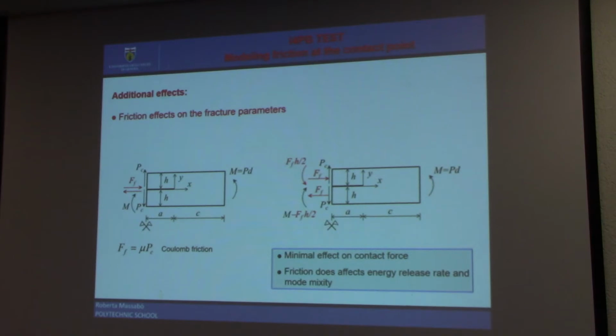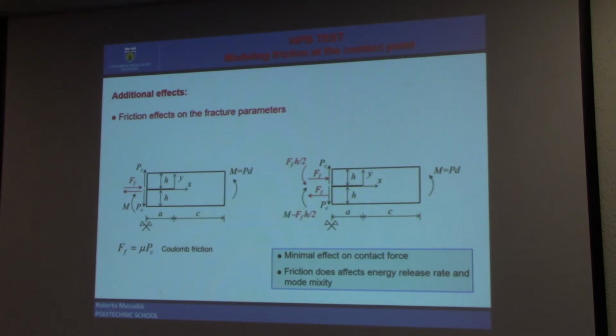So regarding friction, we account for friction using a structural mechanics approximation. Essentially, we consider Coulomb friction, and these two frictional forces are then transferred to the neutral axis of the beam, plus the compensating moment. And what we found out is that the effect of friction is minimal on the contact force, while friction does have a very important effect on the fracture parameters, as we already noticed in Hutchinson's results.